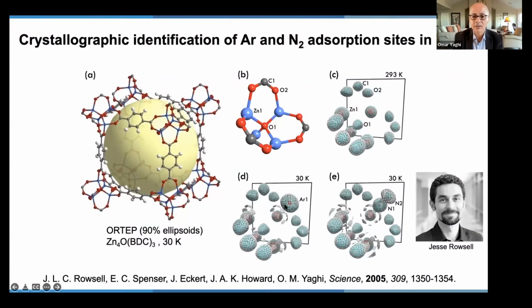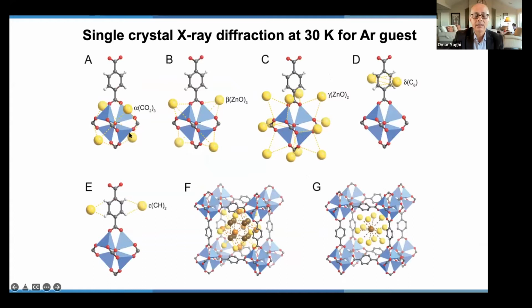you see that they are sticking, or the adsorptive sites lie on the metal oxide unit. But not only that, we find indeed that there are many sites on the metal oxide units. And as you can see here in the yellow balls, that's where argon or nitrogen is binding. These are all binding sites onto the metal oxide unit, as well as we find that there are adsorptive sites on the 6-membered rings of the organic, as well as the edges. So indeed, everything you look at in structure, every atom, every face of the polyhedron linking these structures together is an adsorptive site.